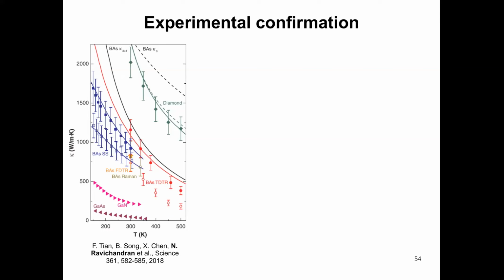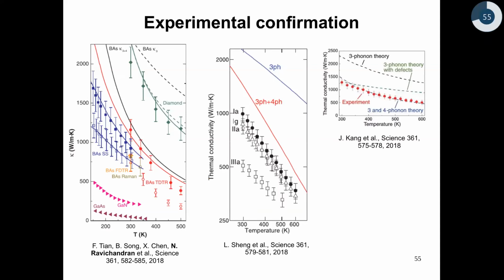In fact, around the same time, there were 2 other competing groups who were also trying to grow boron arsenide crystals, and their experiments are also confirming our theoretical prediction that the thermal conductivity of boron arsenide is strongly affected by 4 phonon scattering. If you look at this middle figure here, the blue curve is the 3 phonon prediction, and their experimental curve matches or roughly matches the red curve both in rough magnitude and also in the trend.